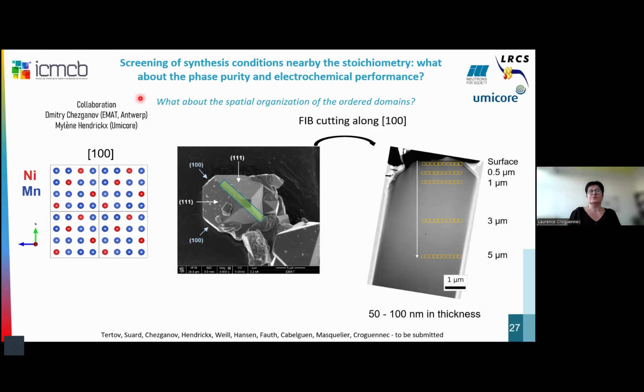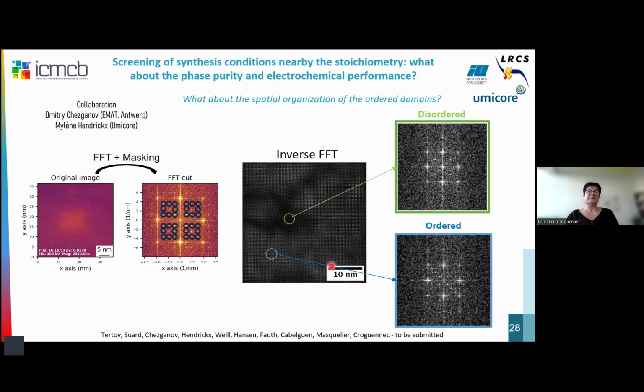This work was performed in collaboration with EMAT in Antwerp and Umicore, with Dimitri and Mylène, and they did this FIB cutting along these directions in our particles in order to have thin layers, 50 to 100 nanometers thick, and to be able to have information from the surface of the particles to the bulk of the materials. And they did different analyses of the images they got by microscopy, combining Fourier transform, masking, and so on.